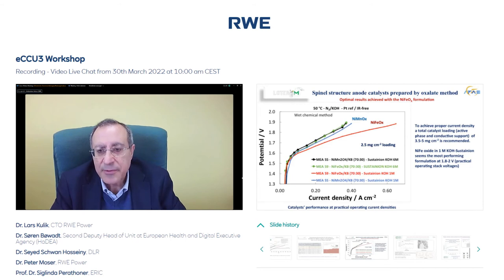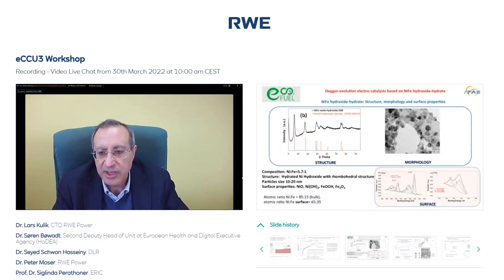Slide number 7, please. So in this slide, we can see that the nickel iron oxide is performing better than the nickel manganese oxide. That means that this catalyst is at present the benchmark catalyst for the oxygen evolution reaction in the alkaline environment in the presence of an ion exchange membrane. And we generally use a catalyst loading in the range of 2.5 milligrams per square centimeter. So there is no significant content of the catalyst used in this electrochemical device.